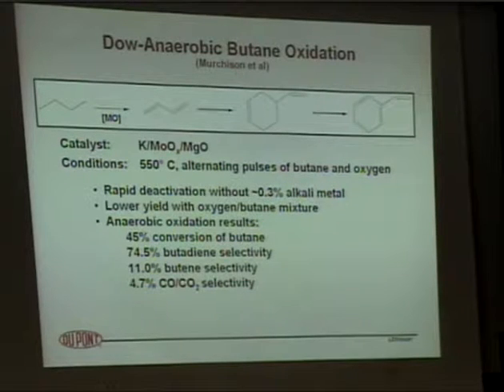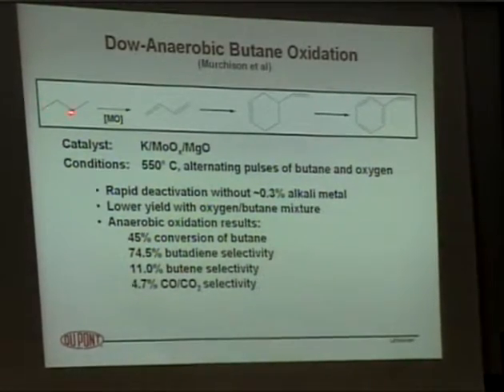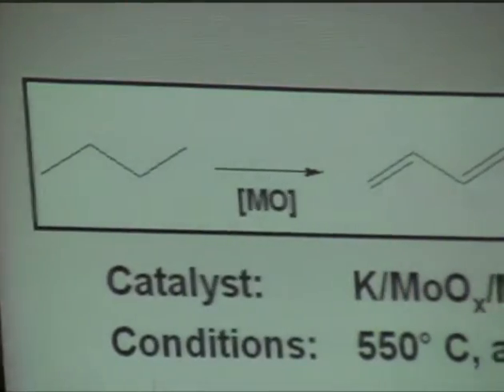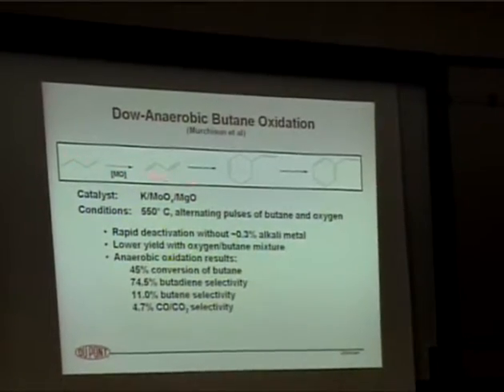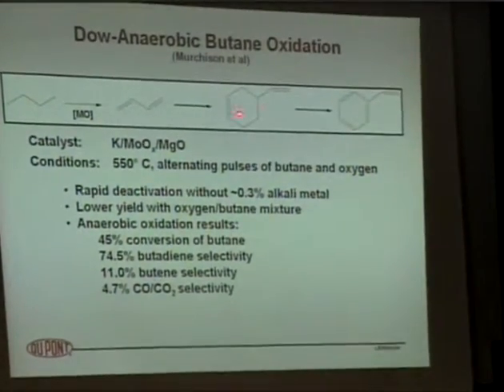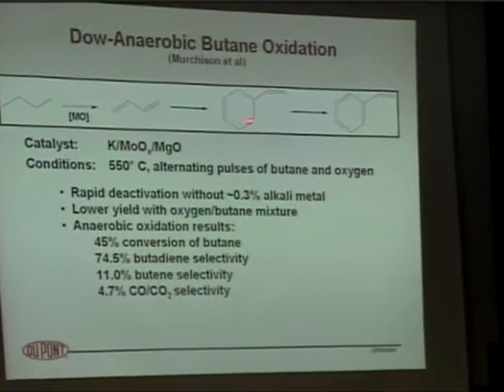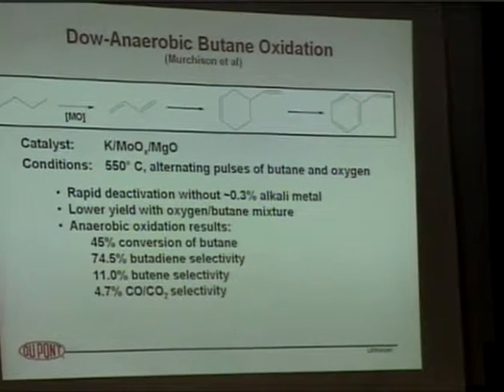Another example that went through the pilot plant stage was operated by Dow Chemical. They were interested once again in making styrene by taking butane, reacting it with a magnesium modified molybdate catalyst to do an oxidative dehydrogenation, with the oxygen coming once again from the lattice of the catalyst, to make butadiene, which they then dimerized to give the vinyl cyclohexene, which then dehydrogenated to styrene. Looked like a great way to go, starting with butane to make styrene.